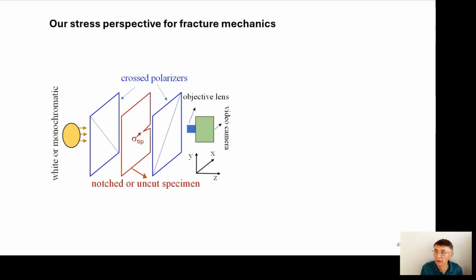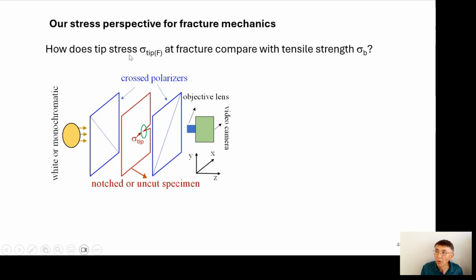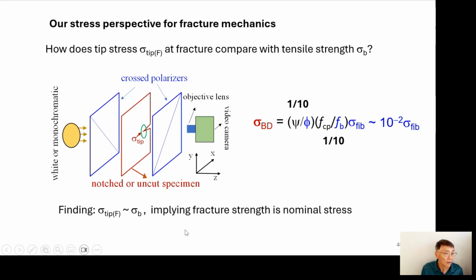So here's our perspective, and it comes very naturally from what we have done for the ductility of polymers. We basically want to answer this question. At fracture with a crack, what is the stress at the tip? Because if I know that, I can compare with my nominal strength. And if they are comparable, then I can claim that there's no flaw that plays any role. So we naively started this way by developing a birefringence technique to look at the tip and see if we can explain why the observed stress is much lower than the fiber limit strength by a factor of 100. Our finding, save some time.